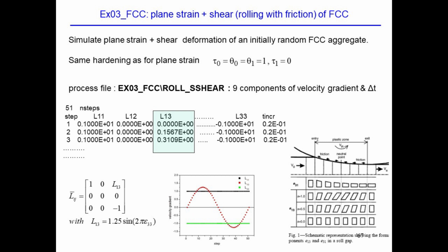So instead of reading that other file that I showed you before with the monotonic law, now the code will go and read this file. You don't need the other file that I showed before. This file can be produced by any finite element code. If you want to know what the texture evolution is in a particular place in your finite element simulation, you can pick an element, and introduce that into the VPSC code using this format, and you can get the evolution of texture and also the internal stresses in the grains in that particular element, or the hardening of that element.